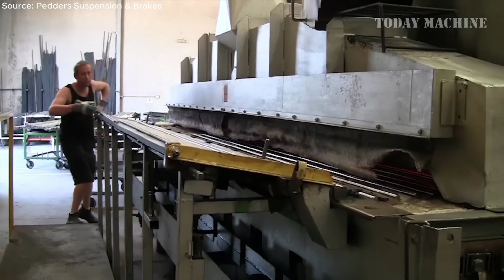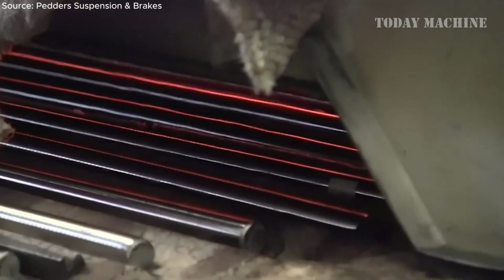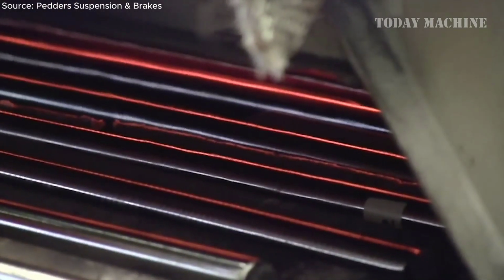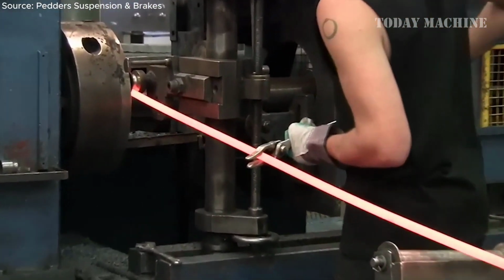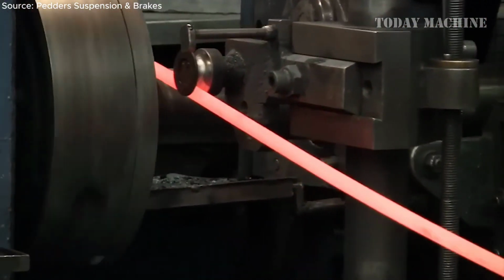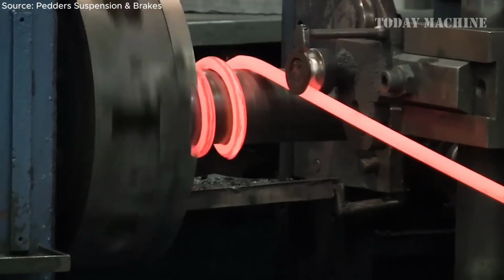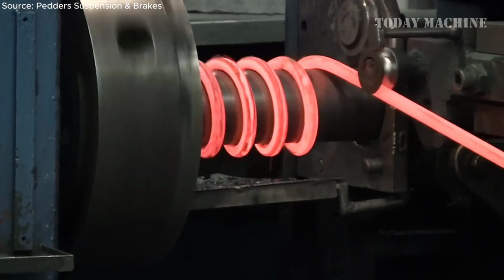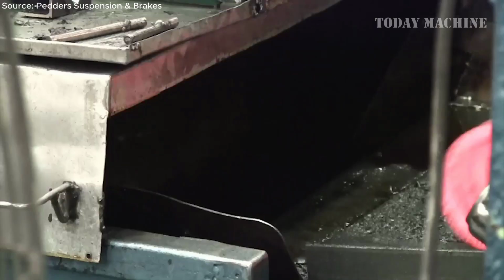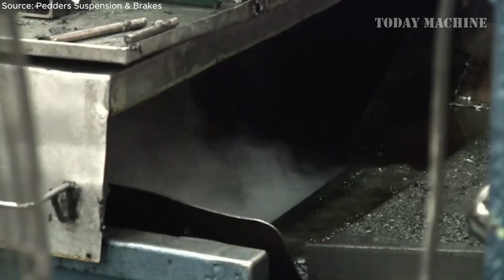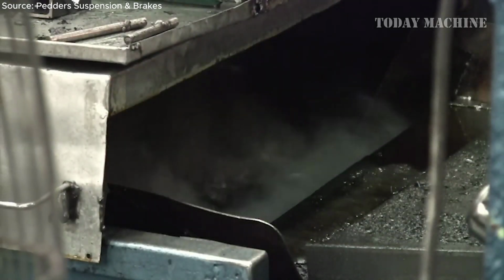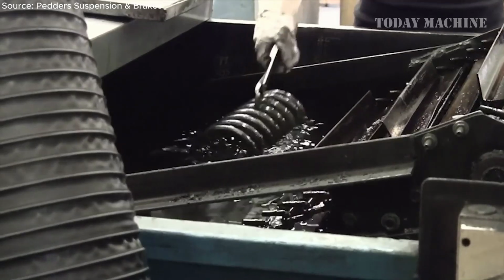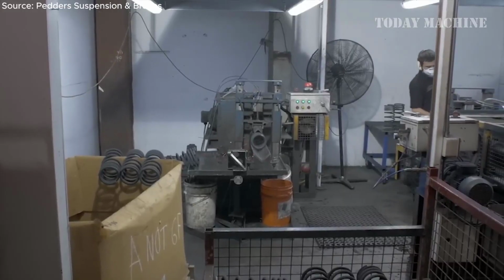The steel is then uniformly heated to 900 degrees Celsius in a gas-fired walking beam furnace, ensuring consistent material properties. After heating, the steel is shaped into coils using a CNC winding machine. The hot wound coils are then quenched in an oil bath for rapid cooling before undergoing tempering in a gas-fired furnace to enhance elasticity and durability.